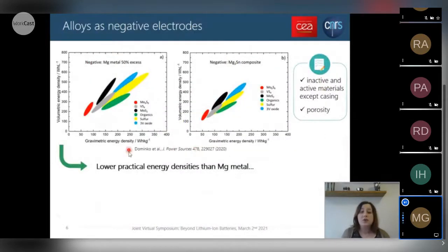Recently, in this review, we tried to assess the capacity and the possibility of using these alloys as negative electrodes. Here we compare their energy density when we look at a system with a negative electrode based on magnesium metal with 50% excess metal, and an alloy-based electrode based on tin. In this calculation, note that we took into account both inactive and active material, binder, carbon, separator, current collector, except casing, and we also took into account the porosity of the separator and of the electrode in the case of the magnesium tin composite electrodes.